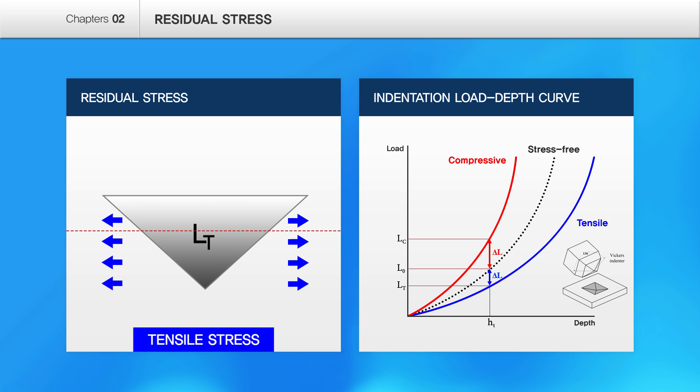Which means higher load is needed to reach to the same indentation depth. The technology of IIT is to evaluate the value and direction of residual stress non-destructively from load difference between stressed state and stress-free state that occurred during these process.